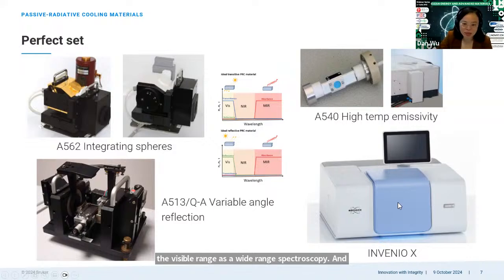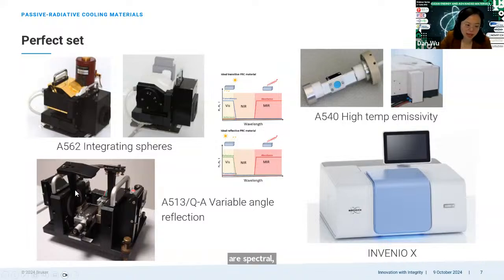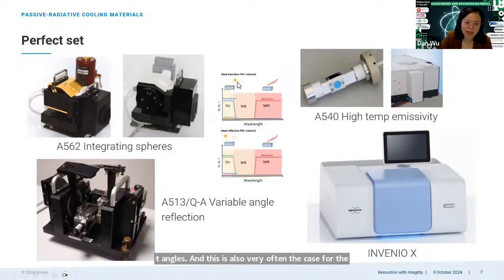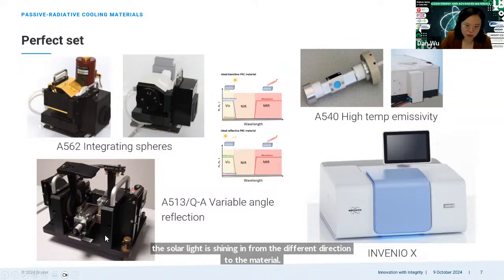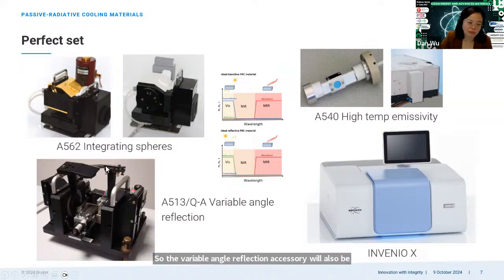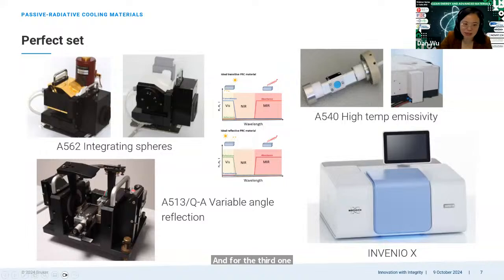And the second advantage of this technique is that you can combine it with different methods to measure, for example, the diffuse reflection, which means that the surface of the sample is not mirror-like. And also you can do specular reflection measurement with different angles. And this is also very often the case for passive radiative cooling because the solar light is shining in from different directions onto the material. So the variable angle reflection accessory will also be very useful for such a material development study. And for the third one, it's the emission accessories directly.